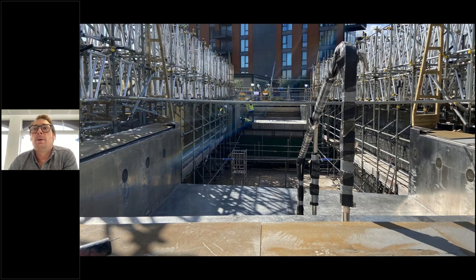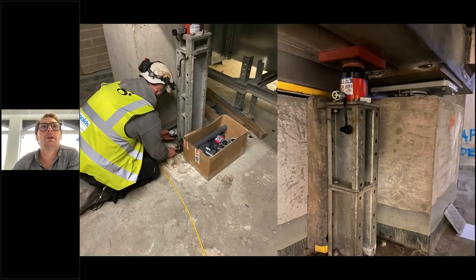And this is the preparation, the prepared area. So we have the steel tubs already in place. We have a lot of temporary scaffolding, to provide access, and you can also see a crash deck below the line of the pool. Within the building, these are showing some temporary jacks which we used to adjust the steel tubs to level. And what we're doing is also putting dial gauges on here. So when we're pulling the tubs together initially, we're making sure that there's no excessive movement on those temporary columns.